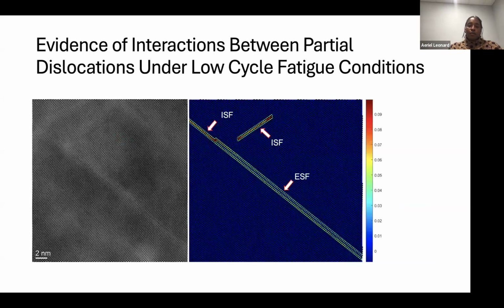And so what we found, when we looked at the low cycle fatigue conditions, is you can see this stair-rod dislocation cross-slip mechanism in action. So we see some evidence. This is in fatigue, where we have this intrinsic stacking fault here from another system that pretty much just interacted with the original ISF and created this extrinsic stacking fault. And so we're actually still investigating these. One thing that we also see in our low cycle fatigue experiments, and so these are tension compression, is slip reversibility. And we're still really investigating that because that's interesting to be getting slip reversibility when we don't get it. Those will be two different mechanisms as we're comparing that to the tensile behavior that we're seeing in the material.